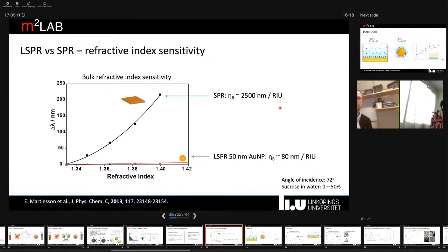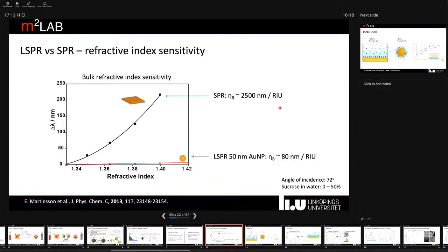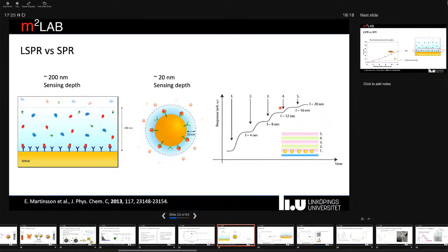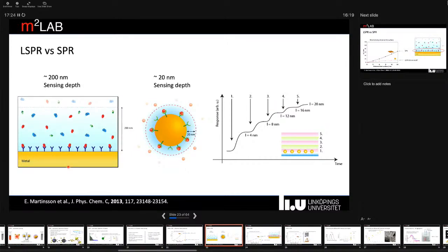If we compare the bulk refractive index sensitivity of LSPR and SPR, there is an order of magnitude difference, or orders of magnitude difference, depending on what particles we use here. And one of the main reasons for this, as I mentioned, is that in SPR we have a quite large sensing depth, so we can detect interactions occurring all the way from the surface to roughly 200 nanometers from the interface, whereas with particles the sensing depth is much more restricted, typically around 20 nanometers, as we can see when you adsorb polymer layers on top of the particles here, the shift decreases quite dramatically.